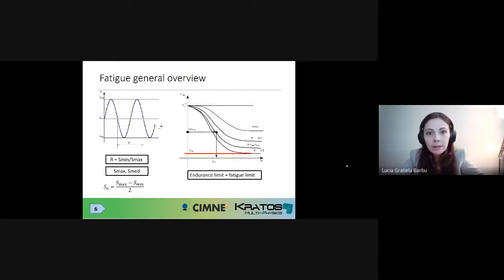An important concept also to understand is that the Wöhler curves, as we accumulate the number of cycles to very high fatigue lives, millions of cycles, tend to an asymptotic behavior for most metallic materials, not so for aluminium alloys, okay? Most metals exhibit this type of asymptotic behavior with large lives, millions of cycles. And the stress level associated to this asymptotic line is the endurance limit, or what is very commonly known as the fatigue limit. And this is the limit that's very important for the industry, specifically when they design for high cycle fatigue loading. Because if you manage to maintain the stress state inside your component below this endurance limit, then you have no fatigue behavior. You will have no alteration of material properties as you apply the cyclic loading.